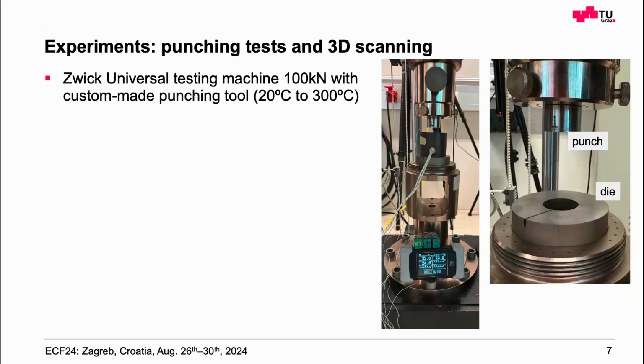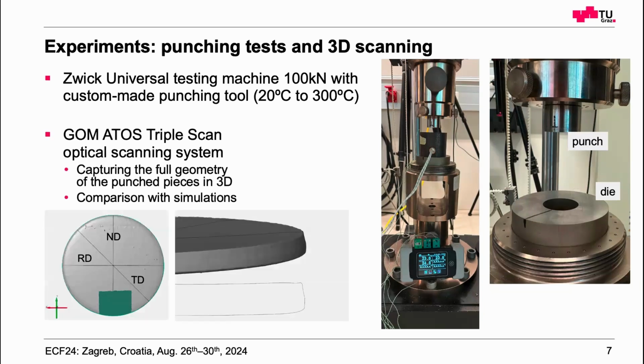To verify our material model we developed afterwards, we built a custom-made punching tool ourselves for our Zwick universal testing machine, which has a maximum force of 100 kilonewton. And there it was possible to punch these copper sheets at different temperatures, so also from room temperature up to 300 degrees. The samples which we produced here, we measured afterwards with our optical scanning system from the company GOM. And here you see such a part which we produced and measured afterwards. And this is afterwards the comparison with our simulations.